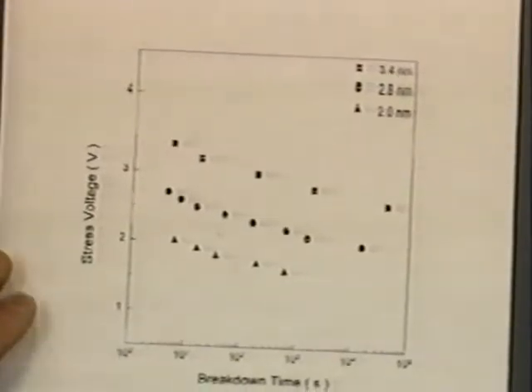This is bad news. This says these devices seem to be breaking down dependent on the fluence or the current that's passing through. It's not independent of this thickness here. You go to thicker oxides, they last longer because you have less current going through them. At least that's what it's seeming to say, that there's no relationship between these. What I would have expected to see is at a particular bias, independent of the thickness, these curves should just lie right on top of each other. But that's not what we see at all.